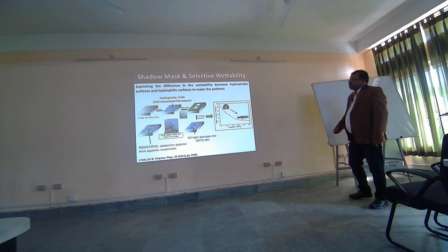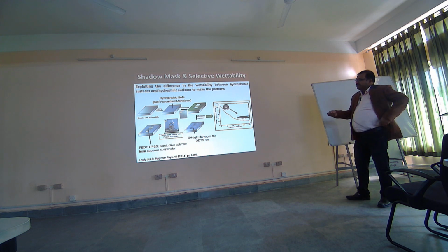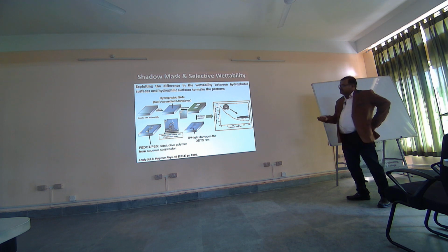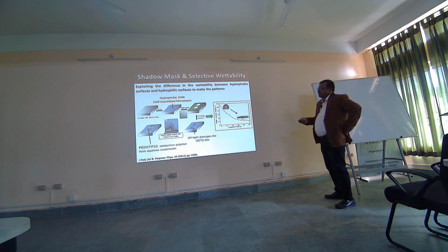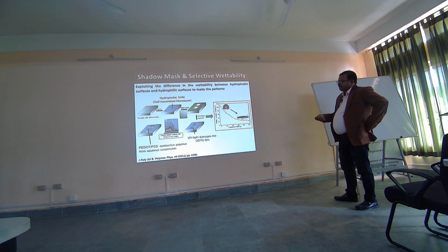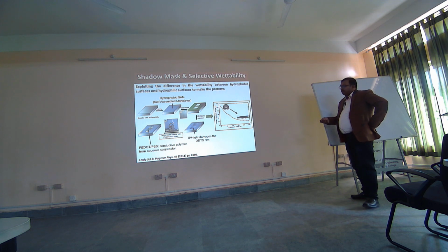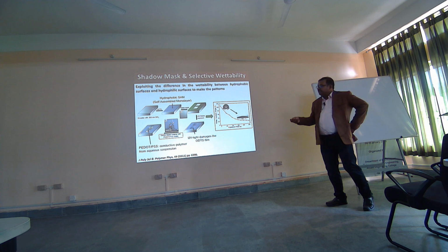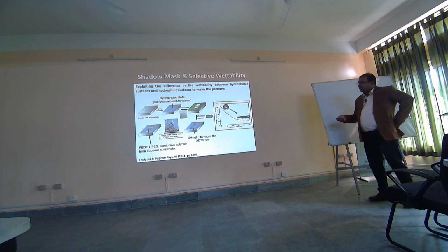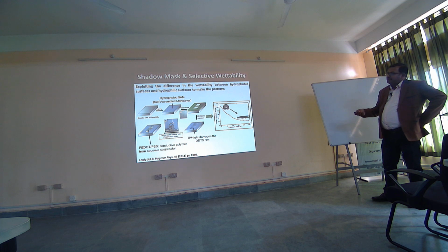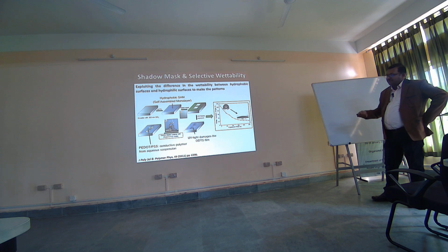Then you have the shadow mask. So this is called a shadow mask. If I make these masks, I can make them using metals. So what is being done over here is, for example, this was the substrate, a silicon wafer substrate, and on this you have an oxide layer on top, an SiO2 layer, and below is the silicon wafer. Then we do a treatment with what is called a silane, octadecyl trichlorosilane, ODTS, and that leads to a self-assembled monolayer, which makes the surface highly hydrophobic.